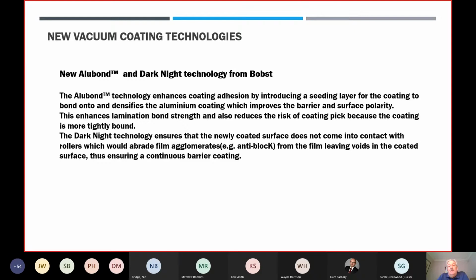And as a consequence of that, the barrier improvement is also enhanced by an increase in surface polarity, which means it's more susceptible to inks and adhesives. And that in turn enhances the lamination bond strength and also reduces the risk of coating pick because the coating is more tightly bound. The Dark Night technology they use is to ensure that the freshly coated film does not come into contact with rollers, which would abrade the film agglomerates.